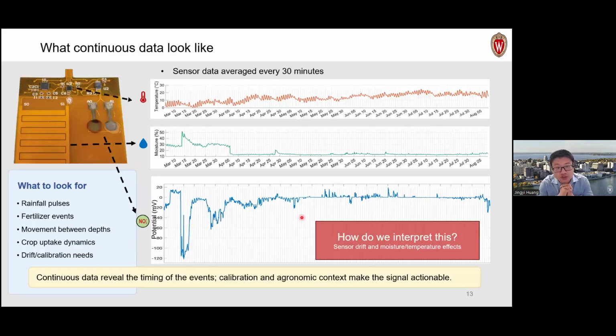So here is what the raw data looks like. We have three panels because we have three sensor components as we described before. The diagram on the top shows you the soil temperature as it warms up from the early spring into the growing season. So we can see the diurnal fluctuations of the temperature. Then the soil moisture, as you see here, tells you that initially during the early growing season for these rain-fed plots, we have a relatively higher moisture, but over time the moisture has been used up, so the soil remains relatively dry.